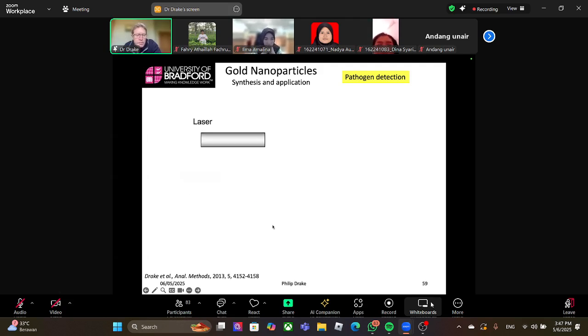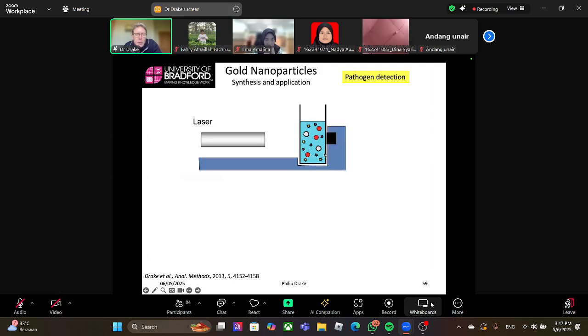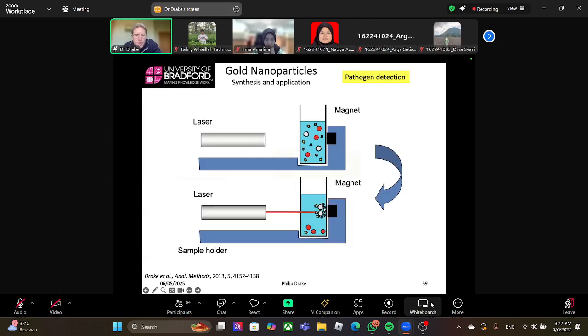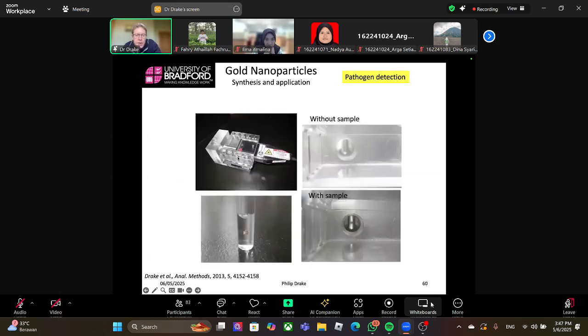detection method. So we take a laser system, we take a solution with mixed things in there, and put a magnet on the surface. Anything with magnetic particles gets attracted to the magnet. Anything with no magnetic labels sinks to the bottom. You then shine your laser onto where the magnet is. The gold particles attached to the bacteria give you a strong signal back to your Raman laser. So this is how the system works.